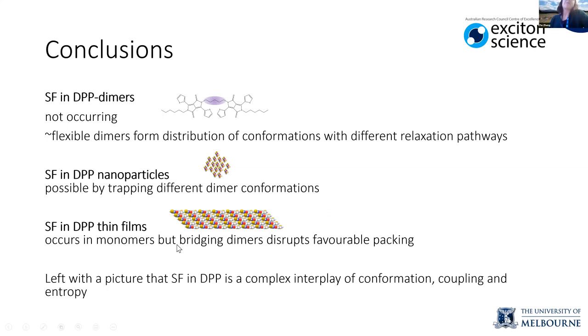And then in thin films, it turns out that having a bridge between dimers actually works against you, and it disrupts what should be favorable packing. So we don't see singlet fission in DPP thin films of dimers. So you can see it's a bit of a complicated story, and it's a bit of an interplay between conformation and the coupling between the molecules.